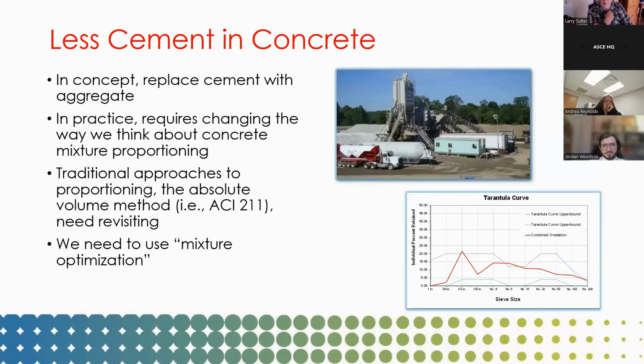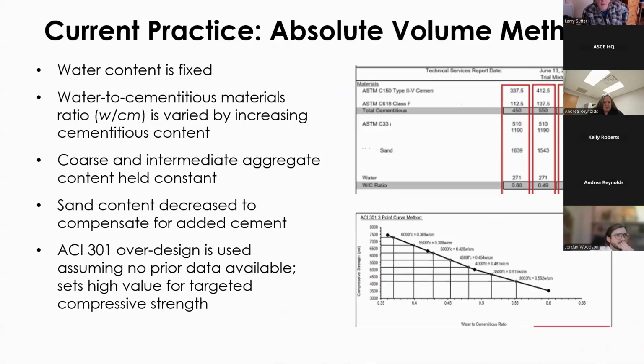Less cement and concrete, we're going to get that through proportioning differently. We need to look at optimized ways of optimizing the concrete mixture, get away from the conventional methods. Next slide. Typically what we do is what's called the absolute volume method. When we do a mix design, we fix the water content, and then we basically vary the water cement ratio by varying the cement content. We hold the aggregate constant, we vary the sand to compensate for the cement. We throw in an over design to meet the 301 requirements, and that's our cement requirement.